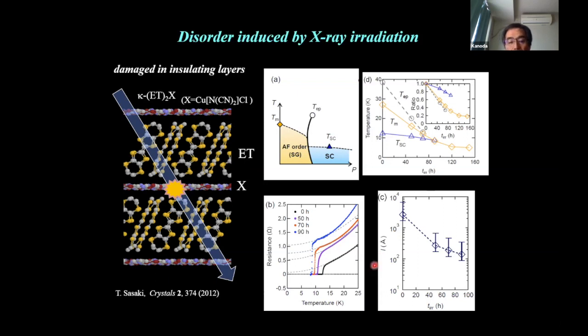We can quantify the strength of the disorder by monitoring the residual resistance in the metallic side. From this residual resistance, we can deduce the mean distance between the disorder centers. The mean distance between the disorder centers is 200 or 300, so very sparsely distributed disorder.